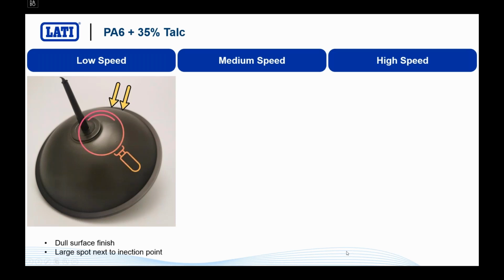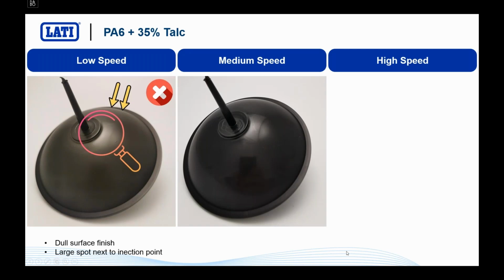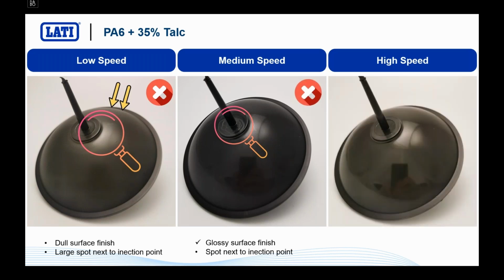What happens if we move up with the speed? By increasing the speed, so by increasing the shear stresses and the temperature of the melt, thanks to higher injection speed, you see that you have quite an improvement on the surface, but you still have some issues close to the injection location. You still have some spots here and there. So you see that your aesthetic is improving with the same material, the same geometry, the same injection location. You can improve your aesthetic, your surface finish, by increasing speed, and you can achieve a very good, excellent result on our polyamide 6 35% talc by using high speed.